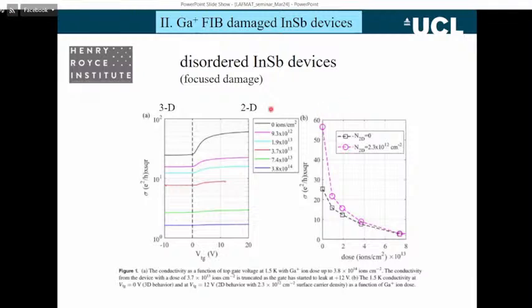Initially, we didn't want disorder in there. We just wanted some manganese doping to make it slightly p-type. Manganese is a p-type dopant. What we found was with ion beam damage, then we could create disorder using damage. So this diagram here on the left shows device conductance. It's plotted on a log scale because we have a very, very strong change in device conductance. The x-axis is gate voltage.